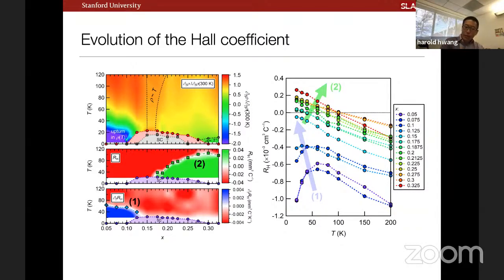Obviously, it'd be lovely to see the Fermi surface by ARPES or what have you, or we can dream of quantum oscillations someday or something like that. I think the qualitative statement would be, too many data here, but this is near optimal doping. The raw Hall coefficient is coming from a negative value and very close to zero at the peak of the dome. So, right, that would qualitatively say that something like the electron density and electron mobility product and the hole density and hole mobility product are roughly in balance in a two-band scenario. But that's probably all we can say at this point.